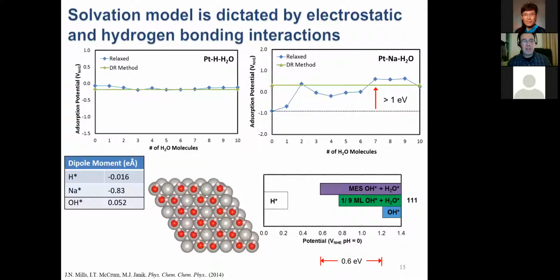Now, how we solvate does make a difference. So when I make our DFT model of a hydrogen on the surface, you might wonder, does it make a difference if that hydrogen is able to interact with water? The quick answer is for hydrogen, it makes no difference. So this is number of water molecules varying in my model versus the voltage at which that hydrogen wants to go on and off the surface. And it doesn't make much difference if I had a few waters around, and this DR method just means a lot of water.